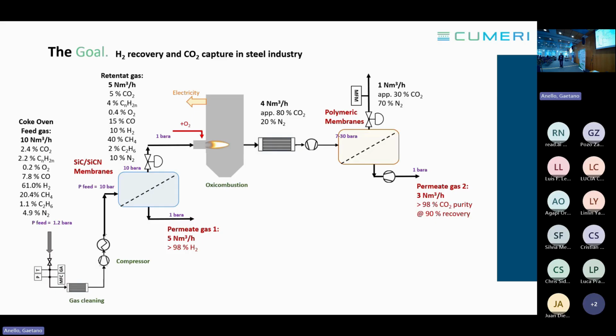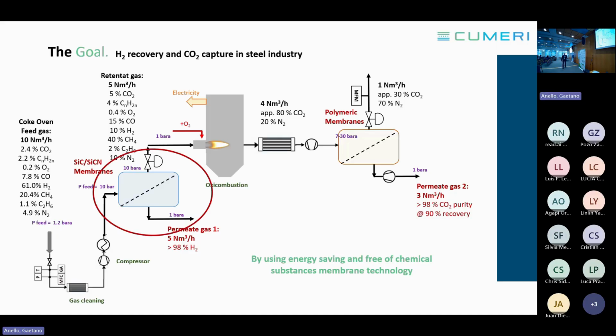Then we are getting a gas stream with 98% or higher CO2 purity, and a gas stream of only 1 cubic meter left from the initial 10 cubic meters, containing 30% of CO2, and we would, by doing this, recover 90% of the CO2. The polymeric membranes are running at low temperature, the ceramic membrane at high temperature. Of course, using membranes is energy saving and free of chemicals, which is very nice. Now in my presentation, I will only speak about this type of membranes,